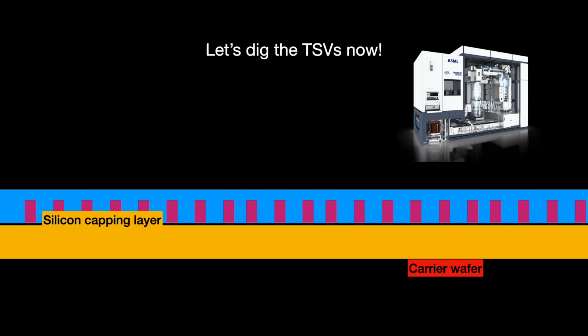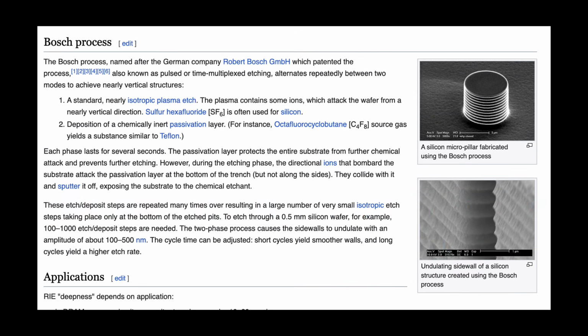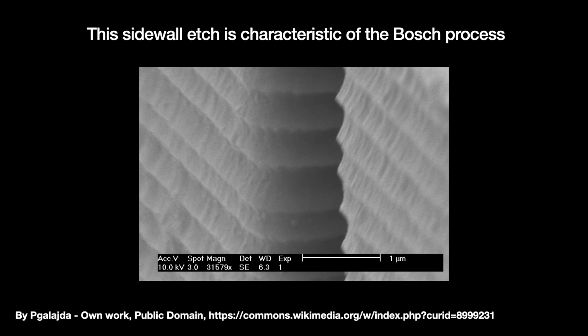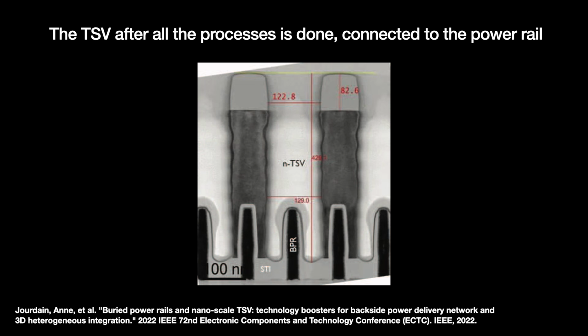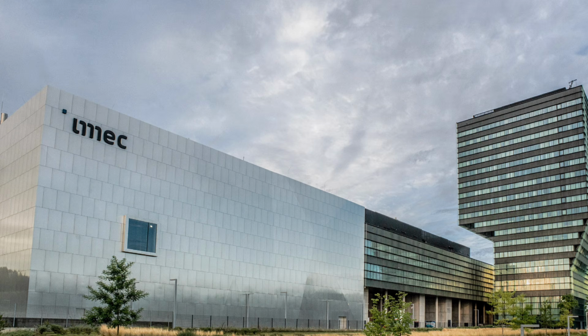IMEC used lithography to tell the etch machines where to dig the vias. Then we use etch to dig the TSVs where the lithography patterning tells us. IMEC used a type of etch called the Bosch process. It works kind of like atomic layer deposition in that it works via an alternating 2-step cycle. First, we fire a plasma of SF6 gas to etch the silicon, then we fire a Teflon chemical to deactivate the etch and keep it under tight control. This cycle eventually drills the TSV, which is about 90 nanometers or so wide. We then clean the TSV, line it with a barrier, and then metallize it with copper to wire it to the greater power network. IMEC has laid out the overall process, and it seems like all the fabs will largely follow it. What the fabs need to decide is on the finer details: tungsten or ruthenium, the width of the TSVs, what liners to use, and so on.